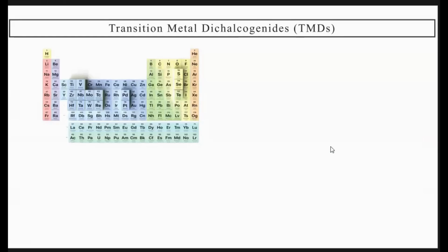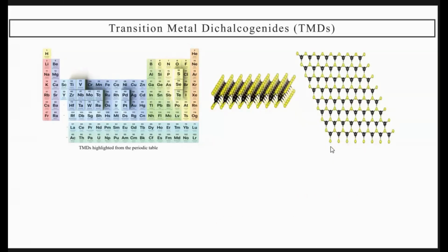So I started with the transition metal dichalcogenide. Transition metal means, as we all know, the d-block metals. The chalcogen family includes sulfur, selenium, and so on. So here I chose palladium and selenium as the TMD. And the structure is very interesting. It is a layered structure. We all know the 2D layering. And here the dark blue colored atom represents palladium, and the yellow color represents the selenium atoms.